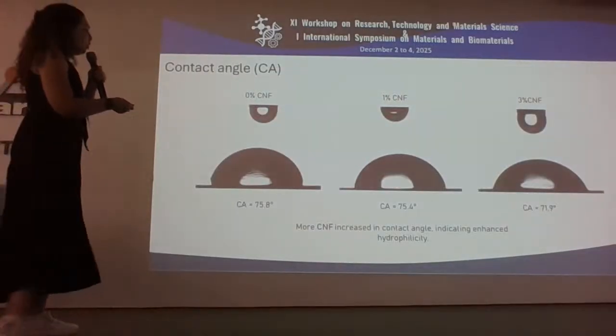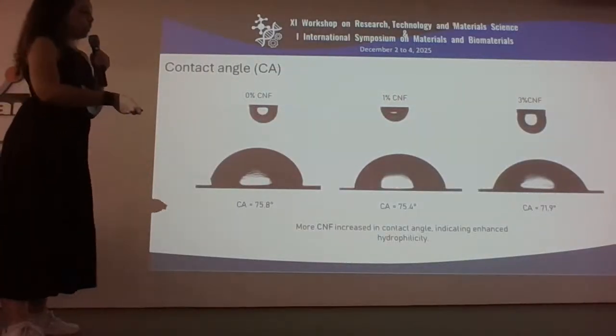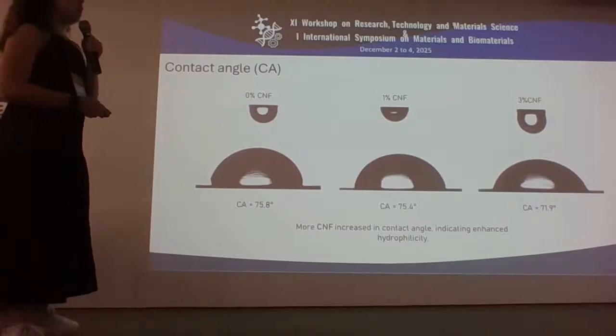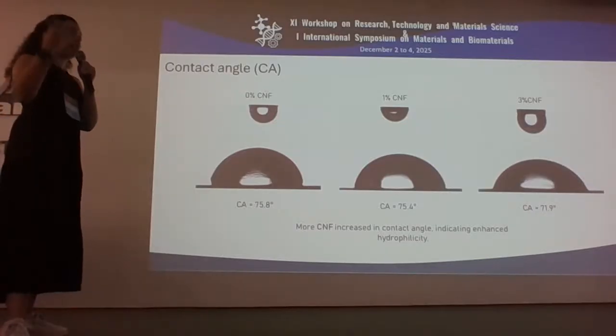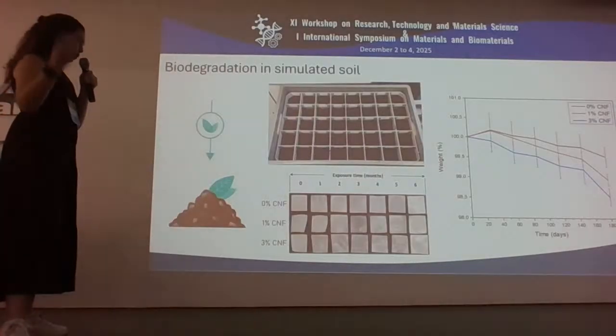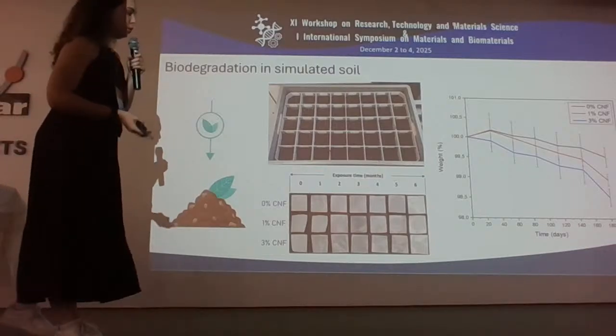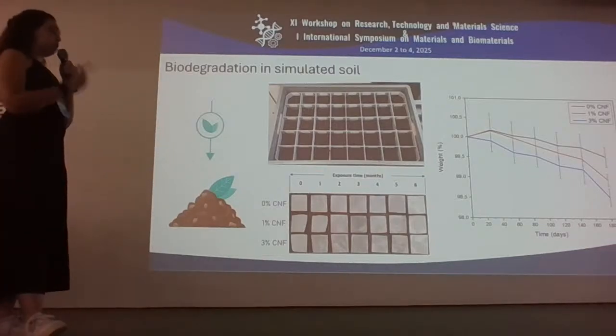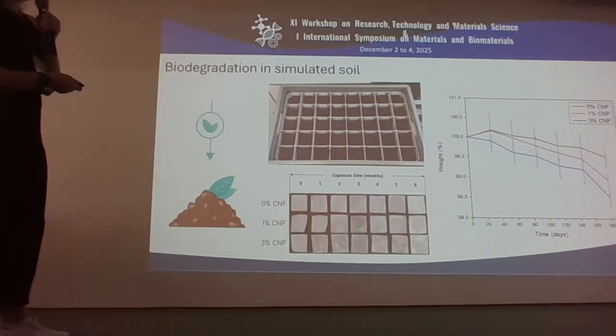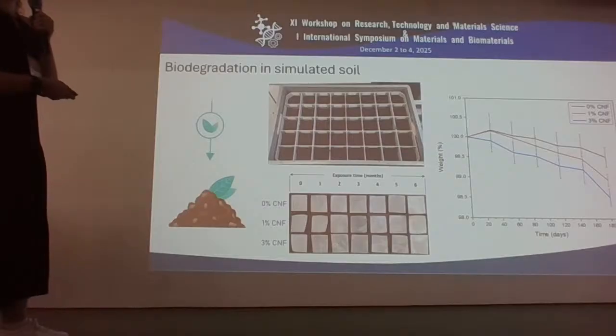But in the contact angle, we have a decrease, and this indicates an increase in the hydrophilicity. And the main result that I'm going to show is the biodegradation. We did the simulated soil for 6 months, and we can see that when we increase the content of CNF, we have an increase in the degradation rate.